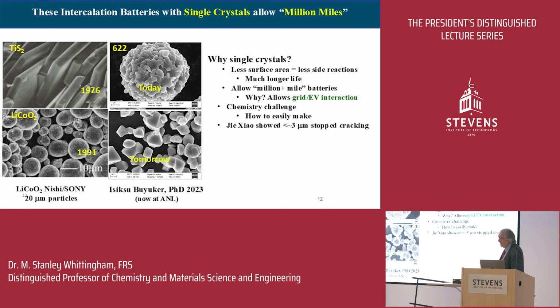So on the top left-hand side here is titanium disulfide, large single crystals. These are up to 1 millimeter on the side and probably 100 microns thick. Beneath that is the original Sony materials, cobalt oxide. They went for as large crystals as they could to make their systems safe. And then what happened, we wanted power. So we went to these meatballs, high surface area, and now there's a big pushback to go back to single crystals. And this is a lot of research going on.